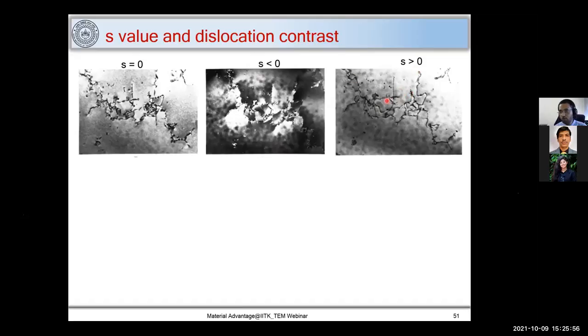So when you want to do dislocation imaging, you should always go for a deviation parameter or excitation error to be more than 0. And how do you do that? Let me again mark it over here. You have a transmitted spot and you have a diffracted spot. You make your Kikuchi line away from this spot. When you do that, you will get this kind of image.